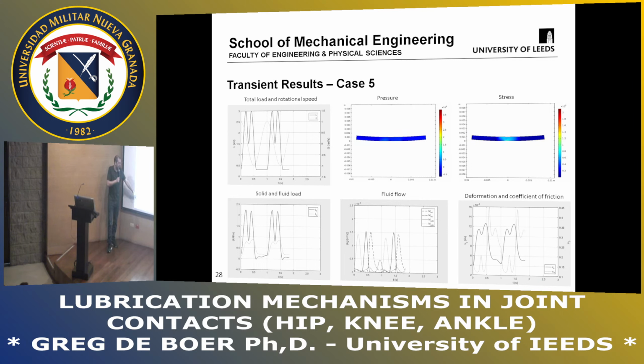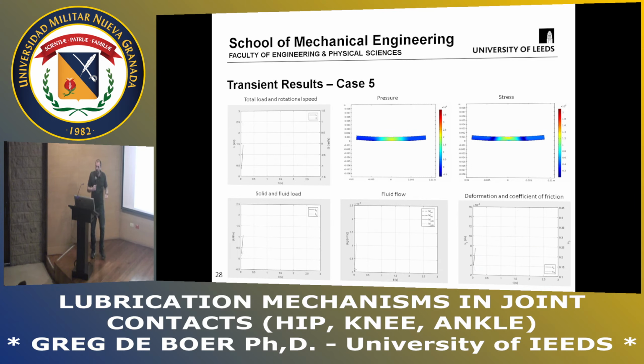Again, this is where the total load of the fluid and the solid are being output, and the fluid takes the load. So as I walk, the fluid is the thing absorbing the load, whereas the solid is almost constant. And only when I have this period where the load is quite constant does the solid actually respond.